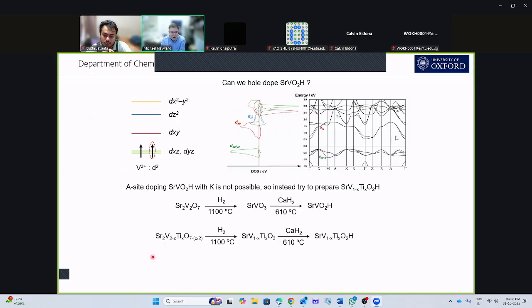So we could imagine now making a starting material at high temperature, which has got titanium in and is likely to be slightly oxygen deficient. And we can then take this precursor under hydrogen to make the titanium substituted perovskite, and then treat that with calcium hydride to make the oxyhydride. And that sounds like a great plan, but it doesn't work.